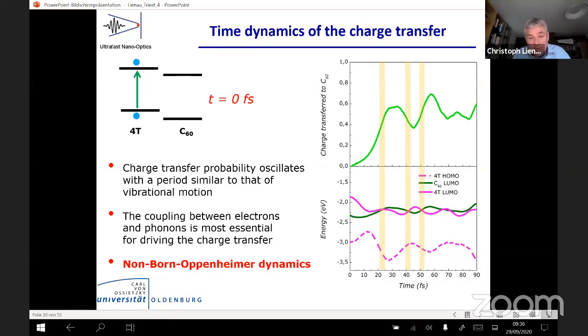So it's very nice non-Born-Oppenheimer physics that we see here for the first time in the pump-probe experiment, and we see that the coupling between electrons and phonons is most essential for driving the charge transfer. And this coherent coupling is, of course, not included in Marcus theory.